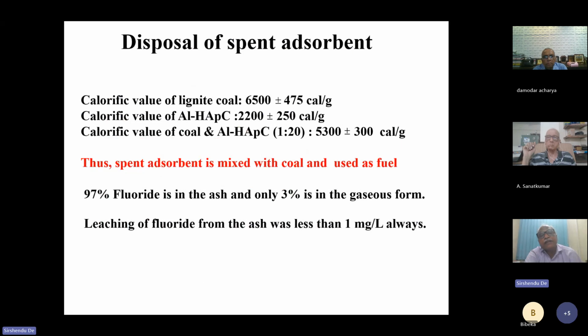The spent media adsorbent is mixed with coal and used as fuel. We have done the analysis. 97% of the fluoride is in the ash and only 3% is in the gaseous form. So it does not contaminate the environment, and leaching of the fluoride from the ash was always less than 1 milligram per liter. So after its life is over, this media can be used as a fuel, and the ash will not contaminate the groundwater, number one, and then in the gaseous form also, we do not have any fluoride contamination.